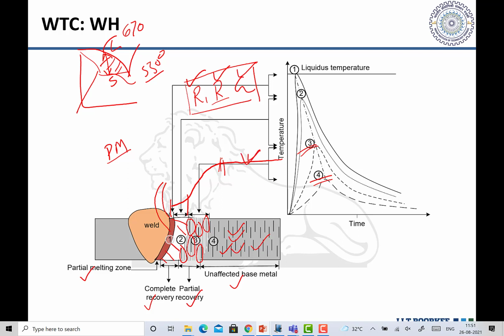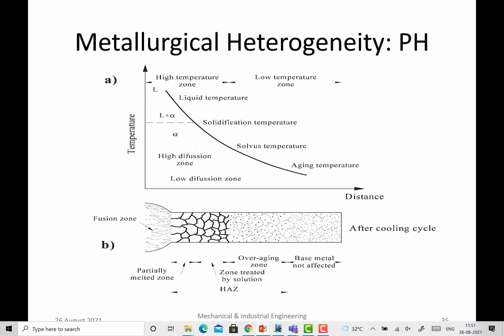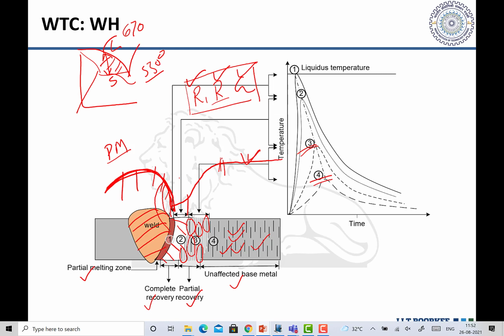So the loss of dislocations will be leading to the reduced hardness, reduced strength, and so this will be leading to the formation of the weak zone. On the other hand, if it has been formed by the solid state joining process, the deformation may cause again the jump in the hardness, because this is the zone that will be experiencing the work hardening effect. And if it has been developed by the fusion kind of process, then everything will be getting lost, only you will have the cast structure. Okay, so this is the story of the heat affected zone of the work hardened metals.